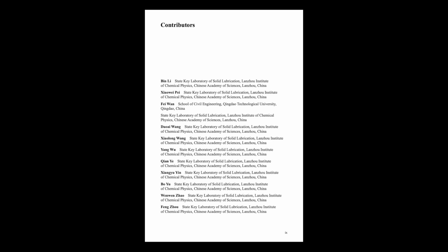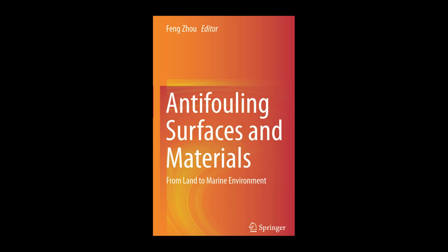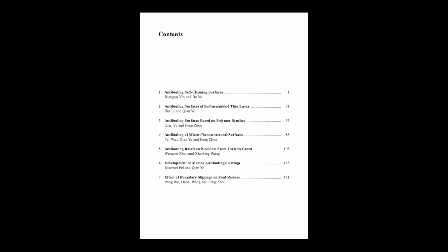Right. So all of that leads to the water forming these almost spherical droplets. These have a very high contact angle, somewhere around 161 degrees. And what's really clever is the sliding angle is only about 2 degrees. Wow. So even a slight tilt and those water droplets, along with the dirt, will just roll right off. And this is a fundamental design principle for us to think about when trying to create these types of self-cleaning surfaces. It's this two-tiered roughness coupled with a low-energy material.